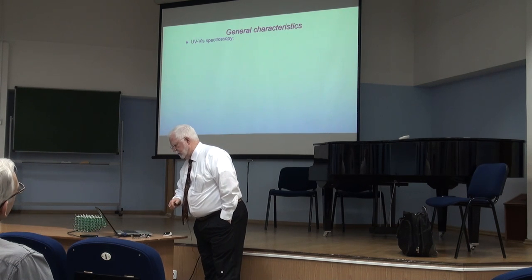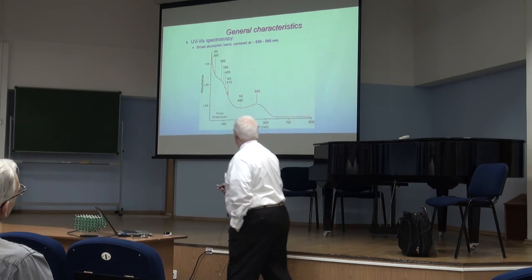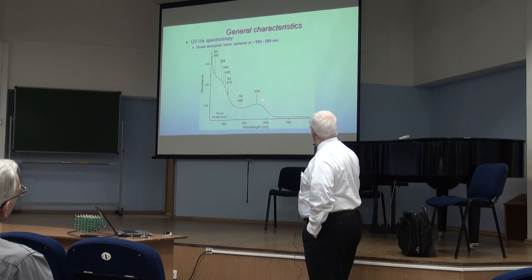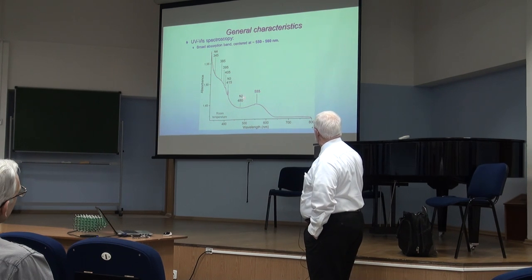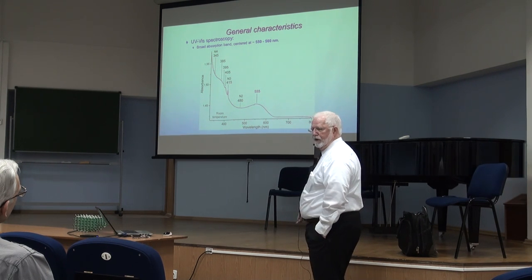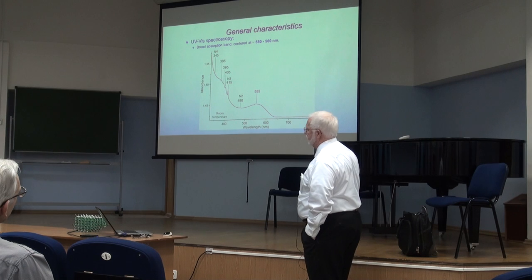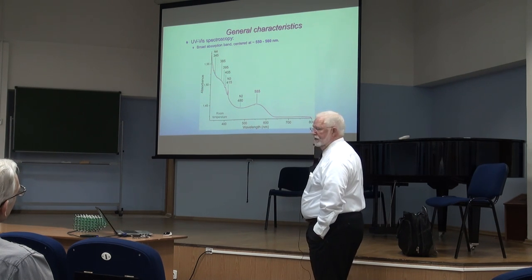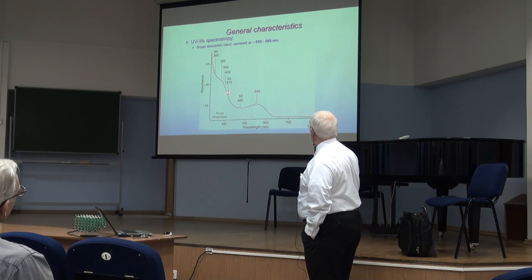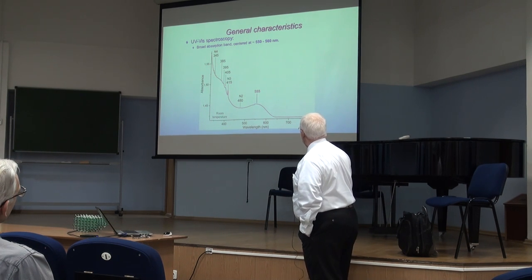The pink color in these diamonds is caused by an absorption band right in the middle between the green and the red. So you have light coming out in the red, and a little bit of light coming out in the blue, which gives rise to the pink color. There are also other absorptions that are well-known nitrogen vacancy cluster states that exist in natural diamonds. This is characteristic of usually Type 1aB natural diamonds.